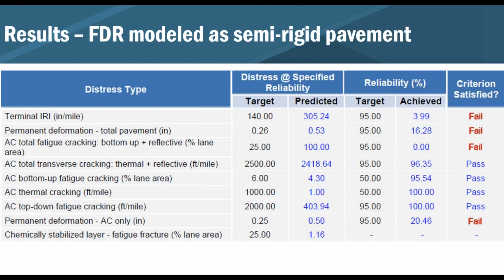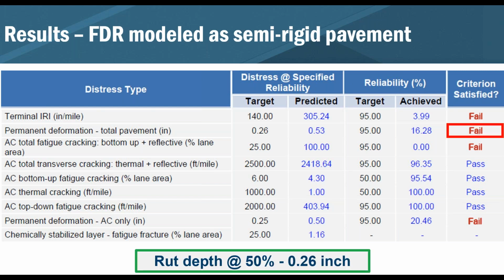All right, so some of the results, looking at it as a semi-rigid pavement for the FDR, looking at the predicted values, and these are at 95%. The IRI is quite high, but again, if we focus on what the Virginia DOT is looking at, it is the rut depth, and at this level it's about twice what they want it to be. But if you look at it at 50%, the rut depth is only 0.26, which does pass the reliability value at that level.